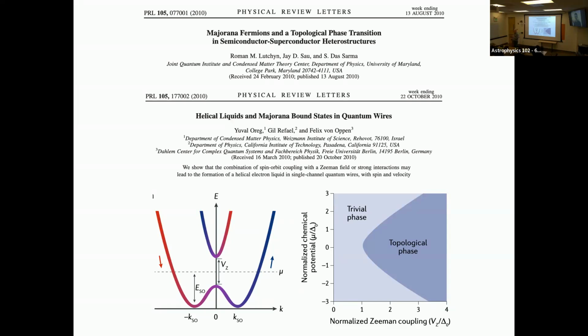Namely, if you apply a Zeeman field, which likes to polarize spins, that exceeds the superconducting gap, which likes to have an S-wave character, you yank the spin like this and it says, forget it, I don't want to be superconducting. However, in the presence of spin-orbit coupling, it's more complicated.